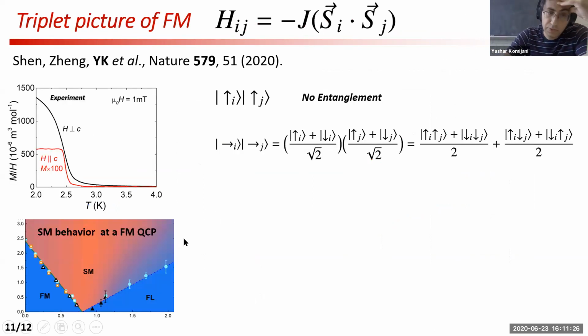And to resolve this puzzle, we have to notice that the system has some magnetic anisotropy. This is the susceptibility measured in the system. And if you measure the in-plane susceptibility, if the magnetic field is in the AB plane, the susceptibility is much larger than it is along the C-axis. Also, when the system orders, the moments are oriented in the AB plane.